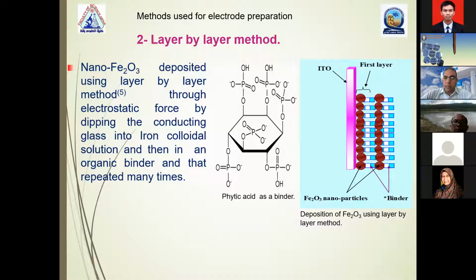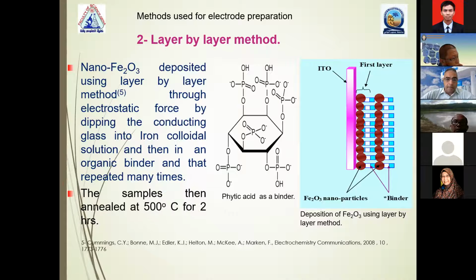and then when it is dipped in the colloidal solution of iron, it gives the first layer, and then another layer of phytic acid makes a binder between the two layers of iron oxide, and so on. We can make many layers, and in the end we can anneal at 500 degrees for 2 hours. So the phytic acid, which is an organic compound, is decomposed and leaves only the iron oxide stuck on the conducting glass. Next.